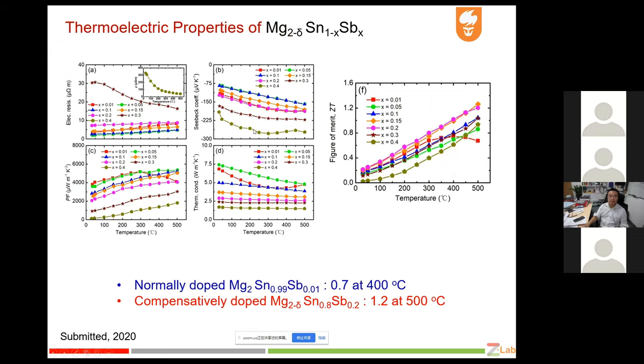This is the thermal property of this antimony doped magnesium compound. Due to the significantly reduced lattice thermal conductivity, the compensatively doped magnesium tin can have a ZT value of 1.2, as compared with 0.7 at 400 degrees for the normally doped magnesium tin with only 1% antimony. The ZT value is increased by more than 70%.